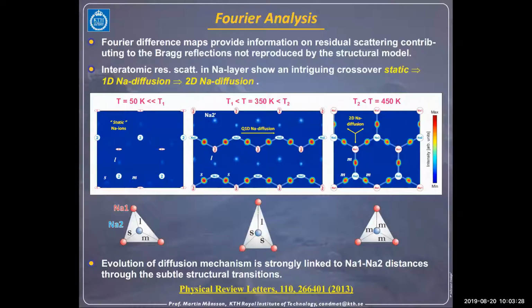So this means that somehow between sodium 1 and sodium 2 there is an intensity in real space. Yeah? And what's interesting is you only see this high intensity where you have the short distance. You see a little bit, but not so much where you have the long distance. So this means basically that you have some sort of jump paths opening up in one quasi 1D direction like this, only where you have this short distance.